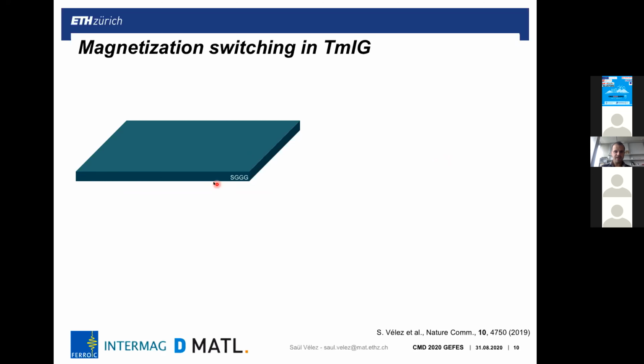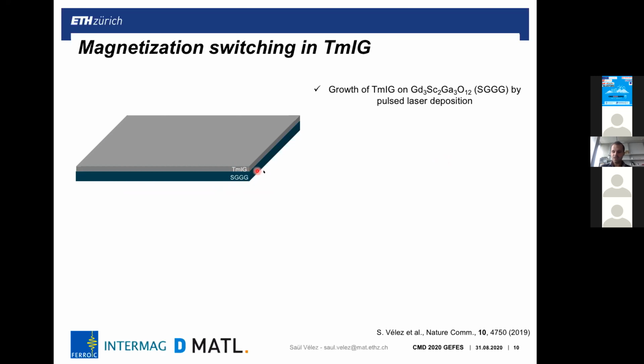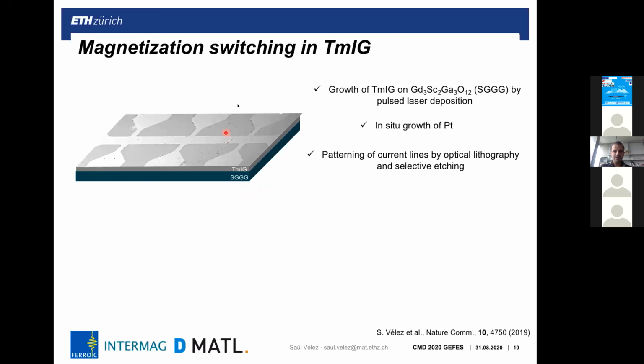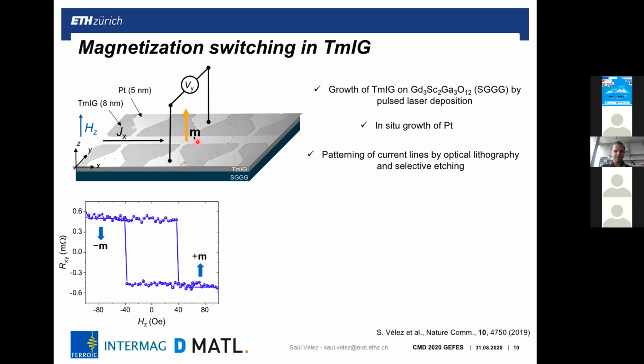Basically our devices are made on substituted gadolinium gallium garnet. By pulsed laser deposition, we deposit thulium iron garnet, and then we in situ deposit platinum to have the best interface possible, and we pattern these layers into this device structure, in which you have a racetrack with Hall bar contacts to measure electrically the magnetization in the system. For instance, here, if we run a current in this direction and we measure the Hall response, we can measure the magnetic orientation of the system, and this shows that by sweeping the magnetic field out of plane, this exhibits a perpendicular magnetic anisotropy, which also is a property that we need to realize these domain wall racetracks.